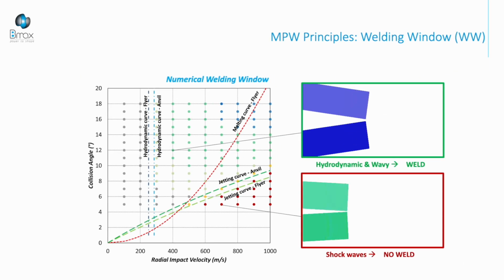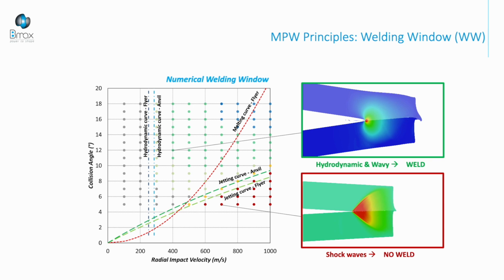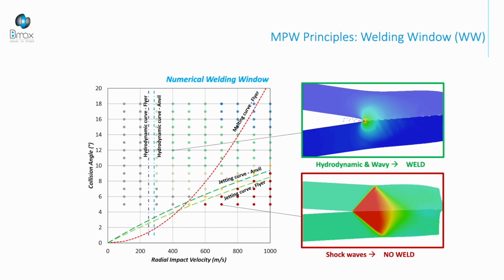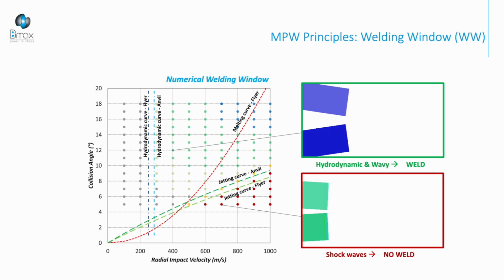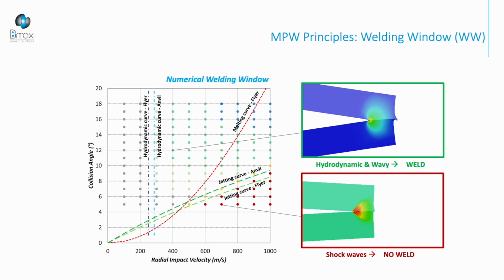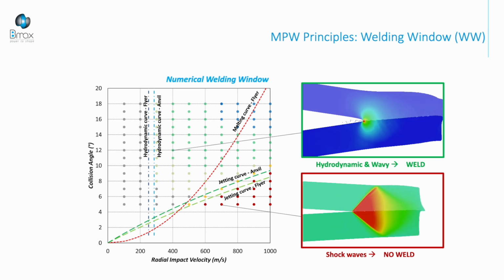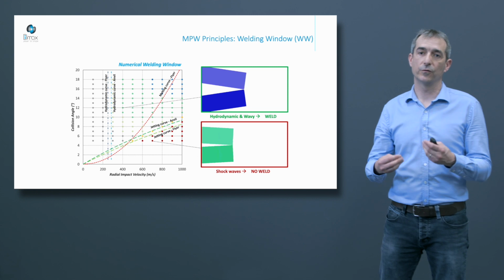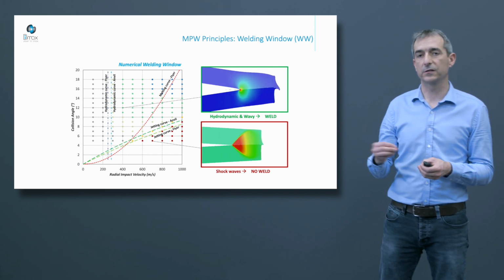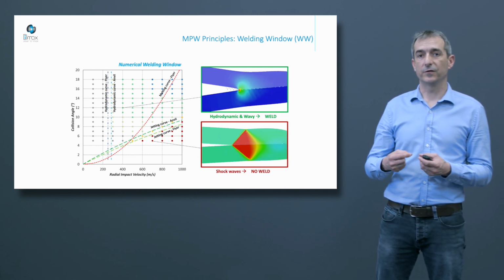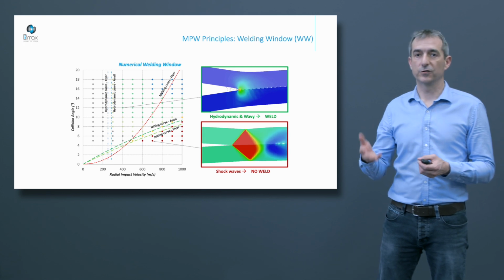In Bmax, we created a new welding window, a numerical welding window, more accurate. We perform 2D simulation in plane strain, and we follow the contact collision for several configurations in terms of angle and velocity at impact. The blue and green points are good conditions to expect a weld, and the red point is when the contact closing is too fast, with a speed higher than the sound speed in the material.